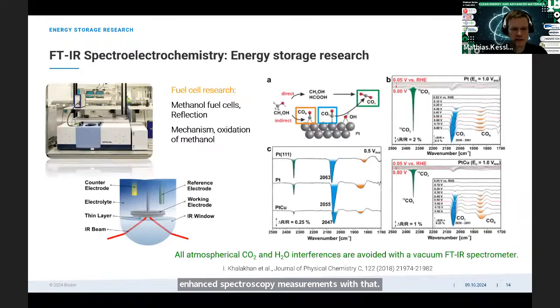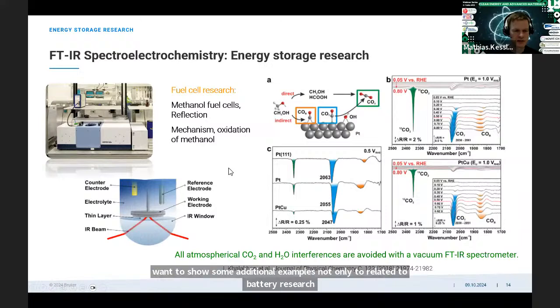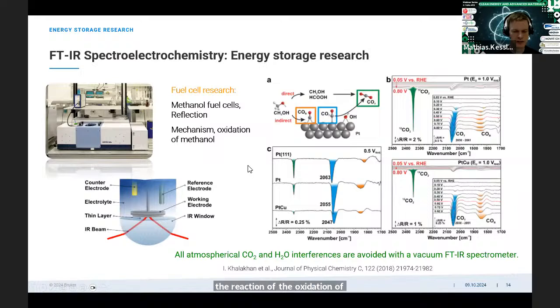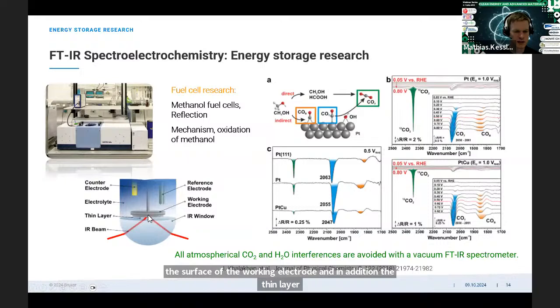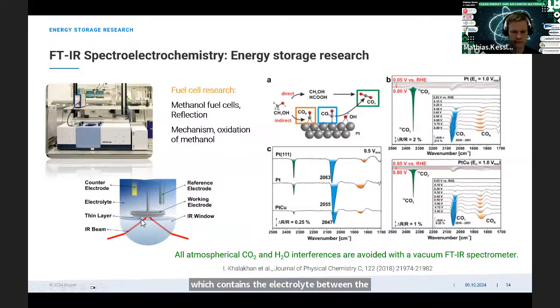I want to show some additional examples, not only related to battery research. We have here the oxidation of methanol, and this is related to methanol fuel cells. And here such a thin layer setup is used where we probe the surface of the working electrode and in addition the thin layer which contains the electrolyte between the electrode and the hemispherical window. And this is a platinum electrode used as working electrode, and then we can see the reactions happening on the surface of this electrode. So we see how the methanol binds onto the surface and is oxidized then to carbon monoxide, which is shown here with the orange bands.